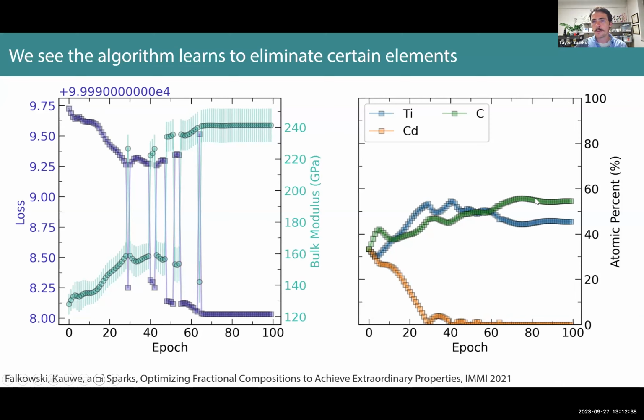It even learned the appropriate ratio of titanium to carbon, that carbon should be slightly rich, which reflects the fact that carbides that are carbon rich tend to be harder. And therefore, you know, it's not surprising they have a higher bulk modulus. So pretty cool that it found that in this scenario.